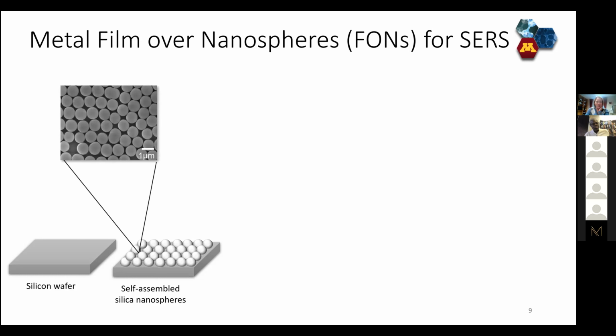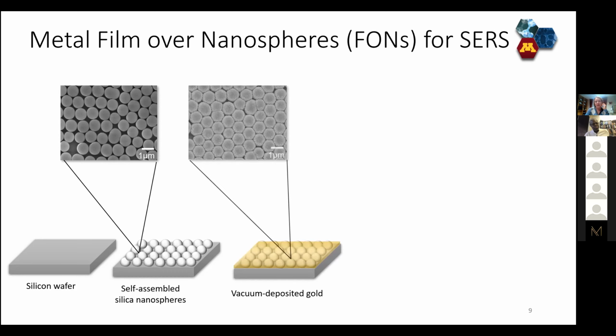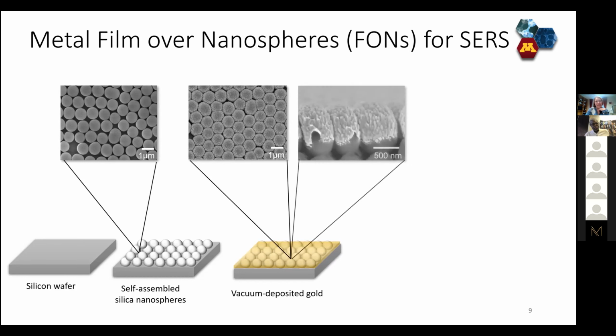Here you can see a little electron micrograph showing you a top view of what those nanospheres look like. Then you can thermally evaporate metal on top of them. And so this is a cartoon where we've put some gold on top of the nanospheres. And now you can see, if you look closely from this top view, that you don't just have the smooth spheres, you also have the kind of roughness based on depositing the metal. You can see this even a little bit more clearly if you split the sample and do a cross-sectional electron micrograph. And so here you're seeing these metal films over nanospheres, and you can really see the gold on the top half and the smooth nanospheres on the bottom.